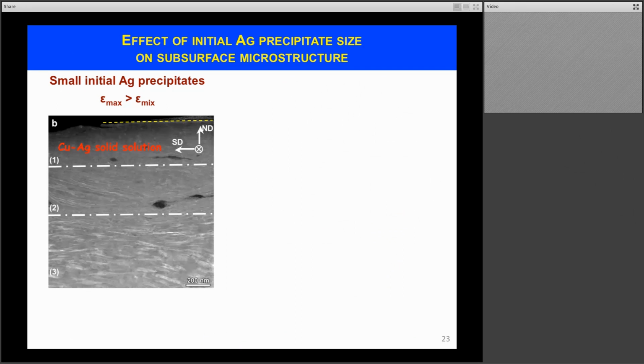Here's a cross-section of this material. The yellow dashed line is the wear surface. And what we see is that far from the wear surface, we have silver precipitate. Then they start to be stretched because of the action of plastic deformation, and progressively we form a solid solution, which is here an indication that the forced chemical mixing is so effective that it dissolves these precipitates. This is for small precipitates.